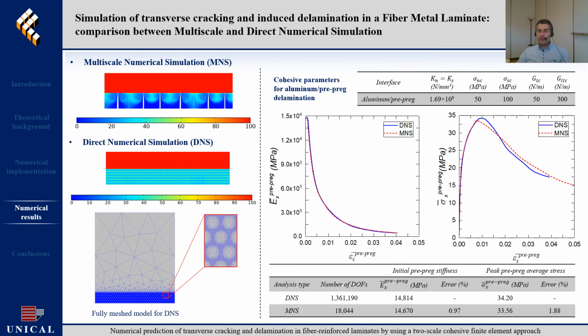After performing the previous offline computations, a macroscale analysis of the considered laminate, here referred to as multiscale numerical simulation, is performed by using as material inputs the previously derived databases. The macroscale response is here reported in terms of global stress-strain relation and homogenized secant longitudinal modulus of the prepreg layer as a function of the applied strain.